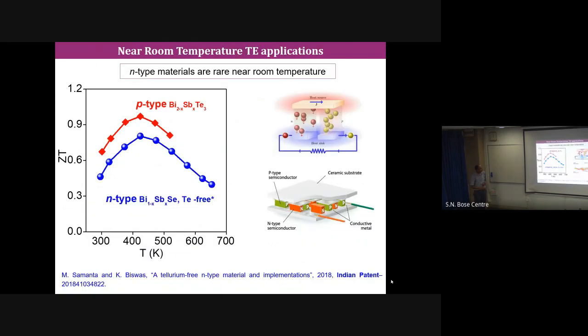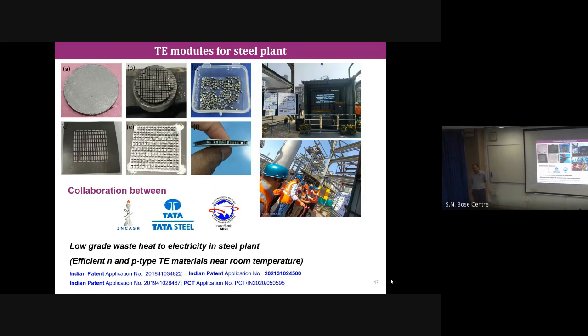So then we have actually patented it because this is near room temperature. So this can compete with N-type bismuth telluride, and selenium is much cheaper than tellurium. We have patented it, and with our patent, Tata Steel started working with us, on P-type and N-type material. With collaboration with Tata Steel as well as ARCI, we made a scale up in our lab up to say 200 grams of this P-type and N-type compound, and these are chopped into small pieces. And we have created multiple legs.